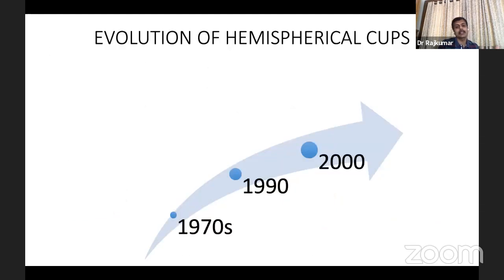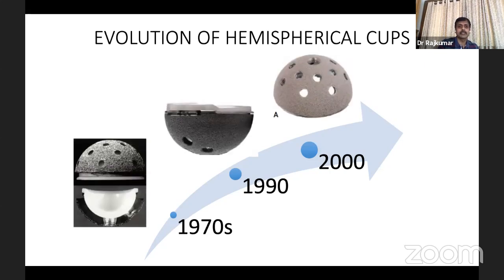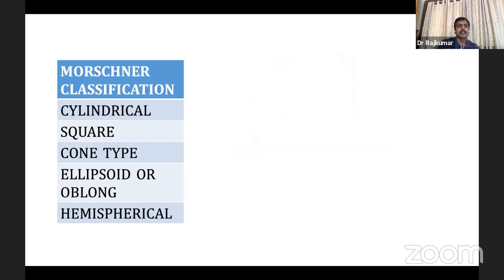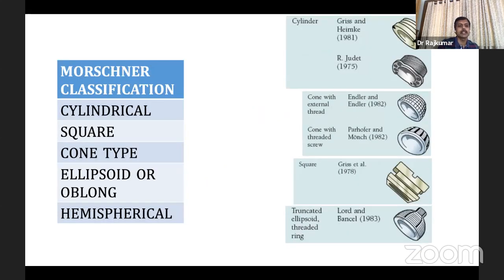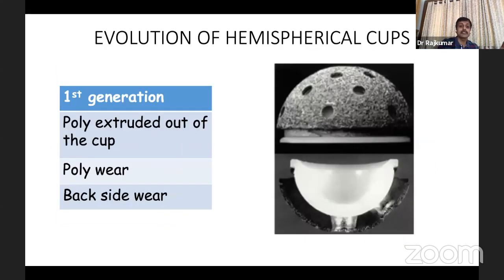The evolution of the hemispherical cups happened from the 1970s to 2000. Once people started seeing a lot of failures in cemented hip systems, these uncemented cups and stems started evolving, and from the 1970s to 2000, the size and shapes changed. Initially it started with a cylindrical, then it became square, cone type, oblong cup, and now it is a hemispherical cup. In the first generation cup, the poly was very thick and it was extruding out. So the wear was very high, and impingement and dislocation rates were high in the first generation.